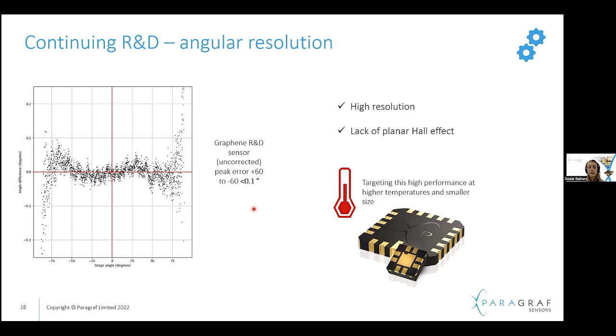So that's a really promising result. Something that feeds into this as well is the lack of planar Hall effect in the graphene. Because we're using monolayer graphene as our active material, we don't have a depth to the device, so we don't see any kind of spurious signals through the thickness of the device. So that's a big advantage for graphene in this.